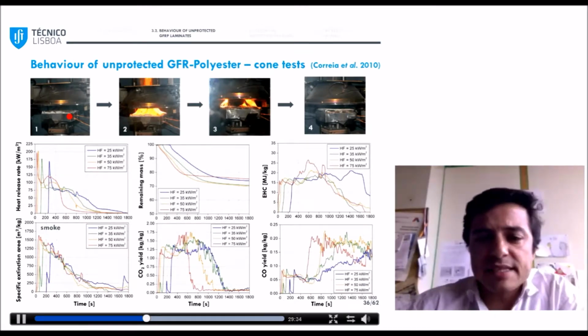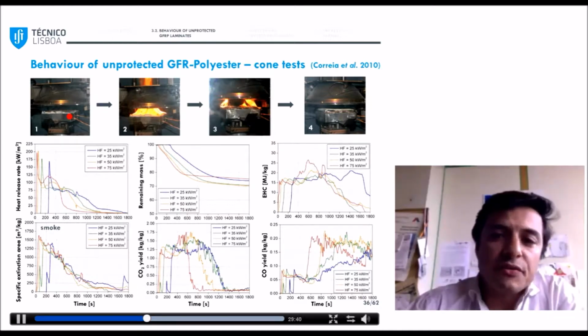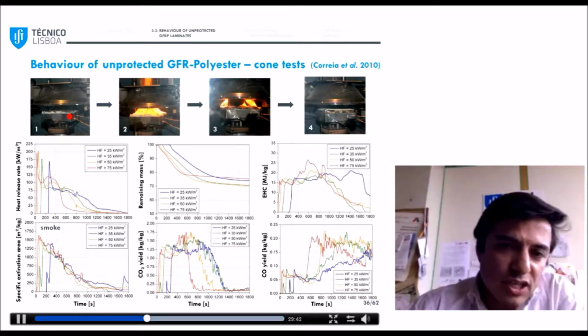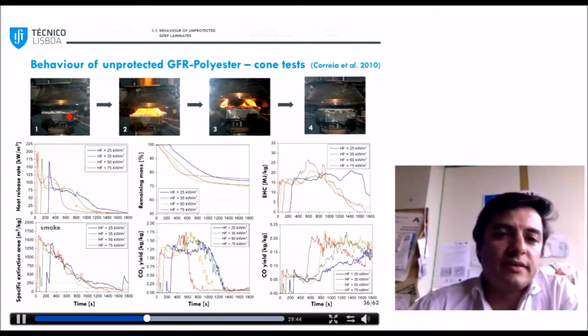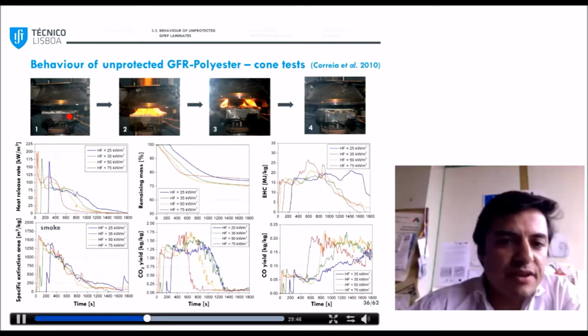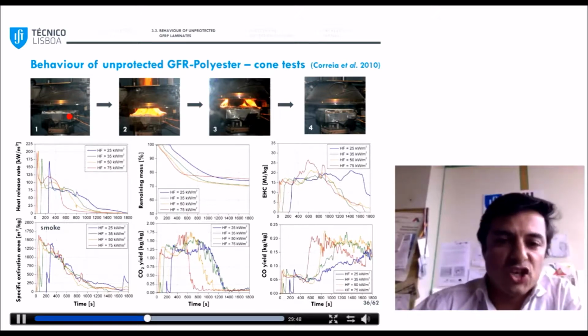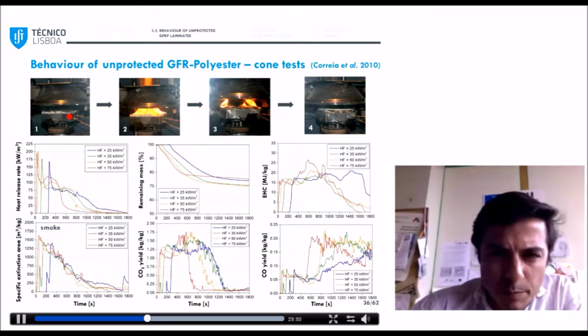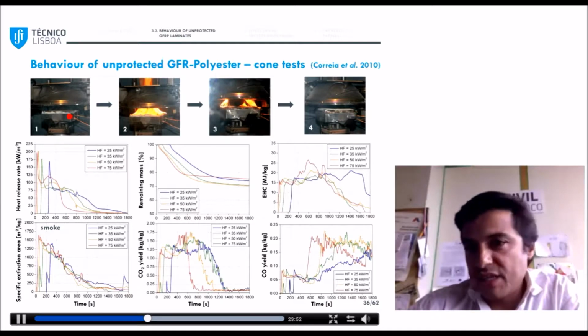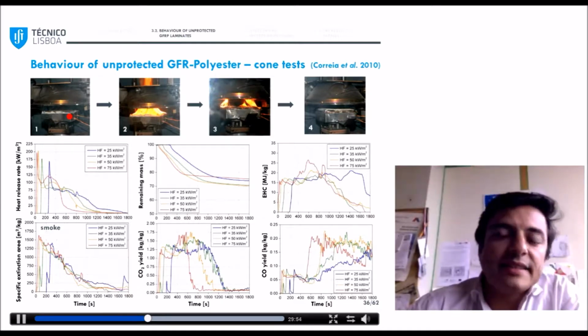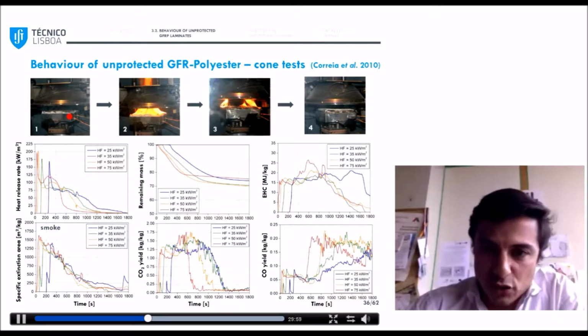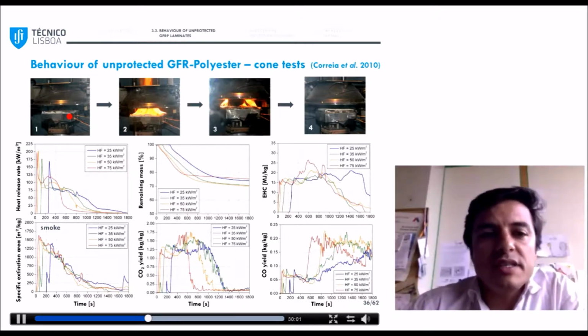At IST, we did some tests in a cone calorimeter on glass polyester laminates under different heat flux, which I show here to illustrate the fire reaction behavior and how different properties change with time. So in the top pictures, you see different stages of the test, and in the bottom, you can see different fire reaction parameters as a function of time.